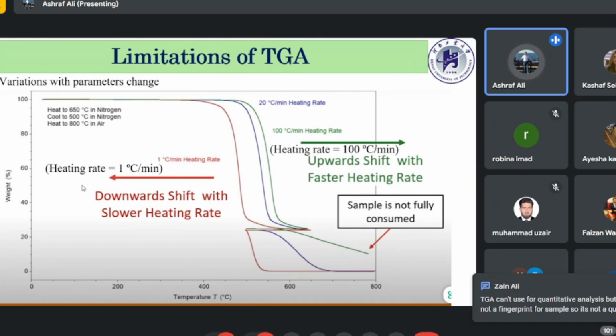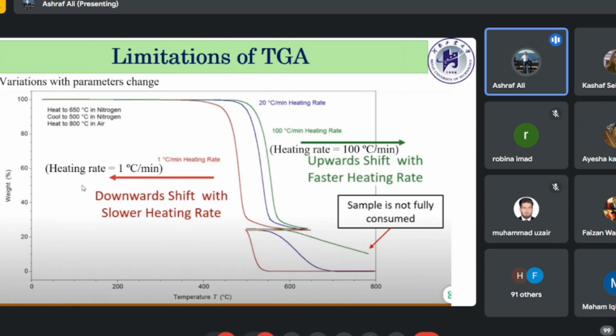Now look here, the decomposition rate and the curves look different from each other, and this is the limitation of the TGA. Even though we have carried out a very small change, like changing the heating rate from 1 degree C to 20 degrees C and 100 degrees C per minute, you can see the curves look very different from each other. Even though the operating conditions are the same, like heating up to 650 degrees C in nitrogen, cooling back to 500 degrees C in nitrogen, and heating back in air, the rate of temperature change per unit time has changed, and now you can see the curve has changed drastically.